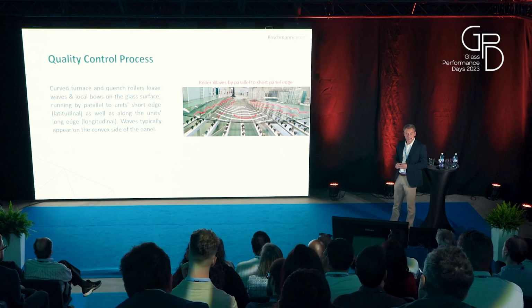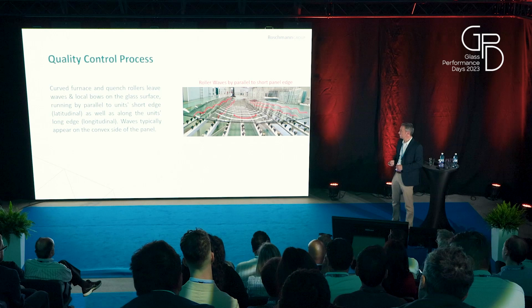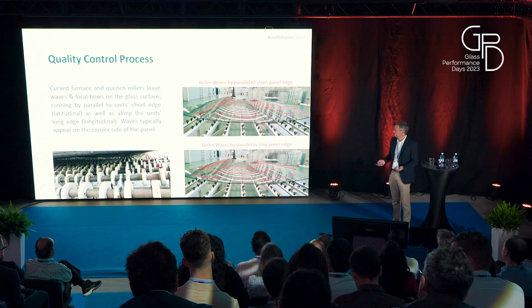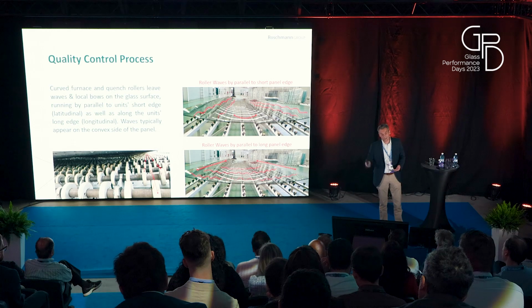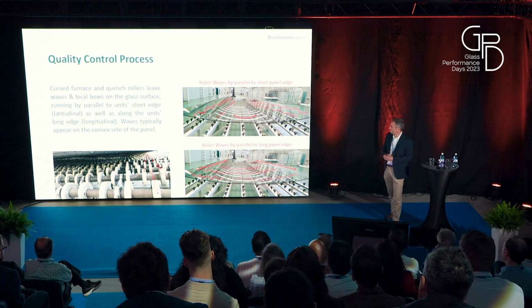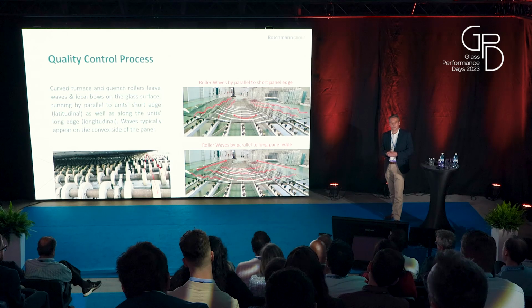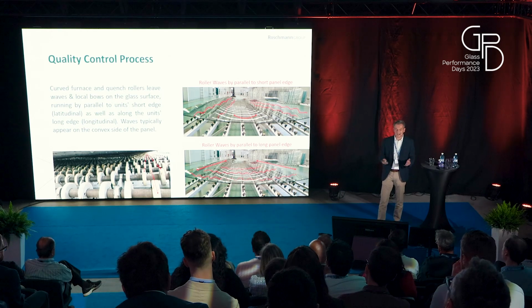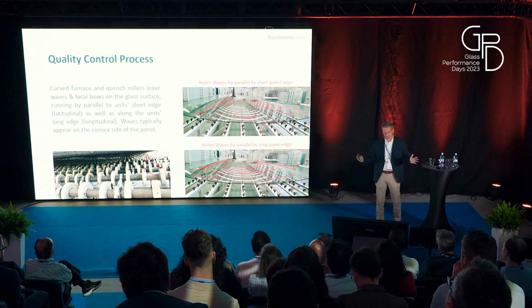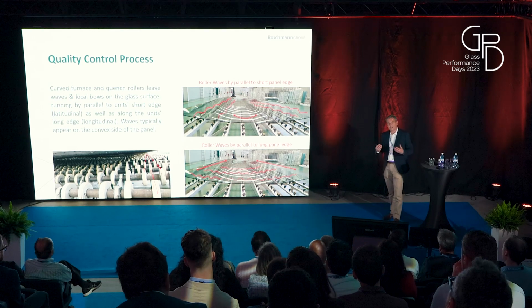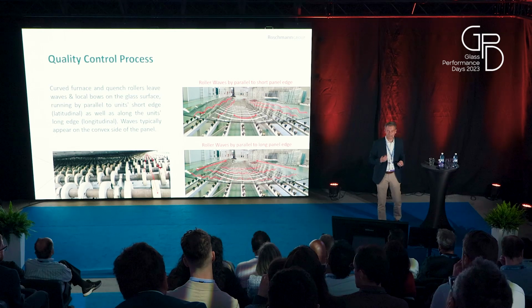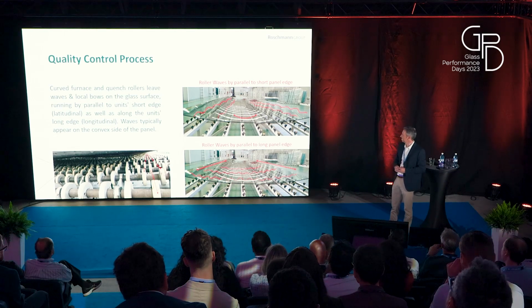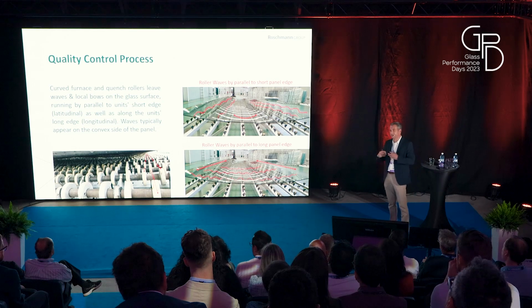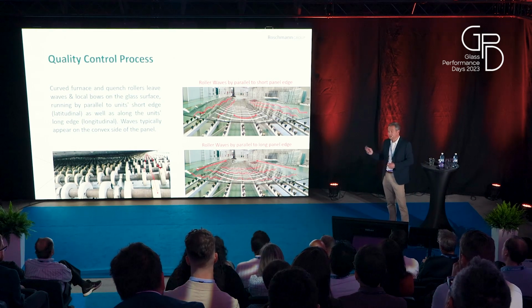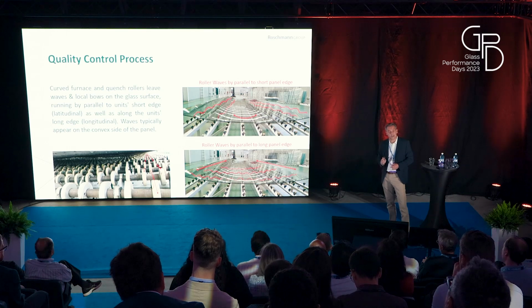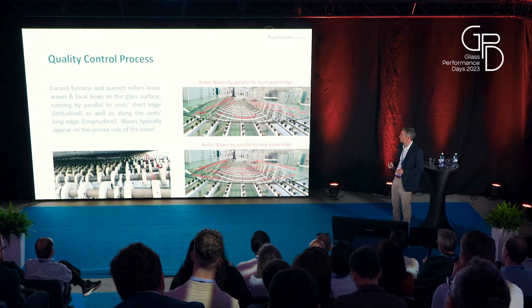In addition to those, in tempered bent glass, I do have another direction of roller waves, which appear parallel to the long edge, because I do have a tempering furnace and a quench, which is mechanically bending the glass and pushing the glass back and forth. This creates another roller wave parallel to the long edge of the glass, which is just creating another distortion on the glass surface. That's a problem because that's also very difficult to measure. That's very difficult to check from a quality point of view.